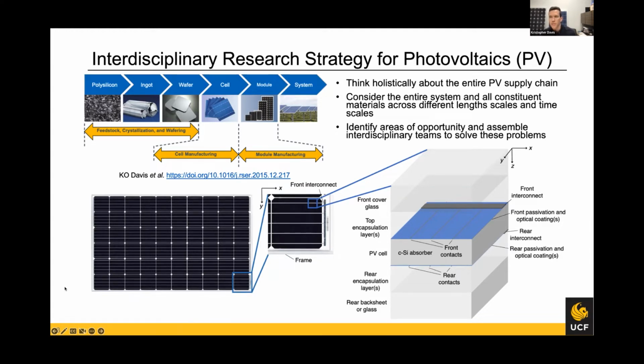And then in terms of time scales, the operational lifetime of these products is 20 plus years. Warranties are typically 25, 30 years. Companies would like to move to 50 years even. So we have to consider these long time scales and have models for various degradation mechanisms. But also, in some of our measurements, we're looking at charge carrier lifetimes on the order of microseconds, milliseconds, and even shorter. Those are for good devices. Some bad devices have even shorter carrier lifetimes.